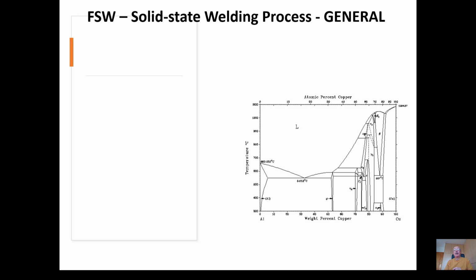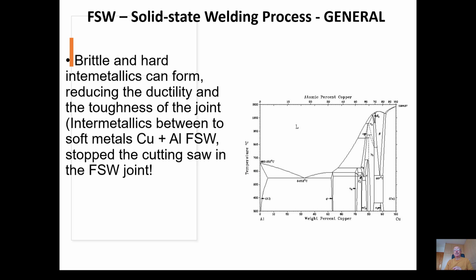being made. Another generality about friction stir welding is that brittle and hard intermetallics can form. Right down here, the theta phase and this eta phase. This happens to be the aluminum copper phase diagram, and you can see the differences. Here the copper melts at 1080 C, like aluminum at 660. So you have this very wide difference in melting points.